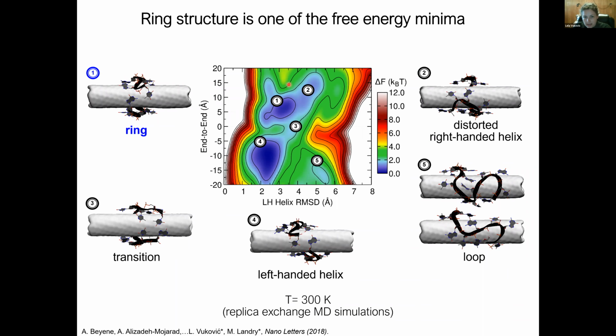And here is a free energy landscape. It's a 2-dimensional contour plot in terms of the relevant reaction coordinates in this system. What you should pay attention to is the color of the contour plots. The color represents the free energy of the system. The dark blue regions are free energy minima for these systems. Those are the conformations that the system likes to adopt. If you see red and other colors, those are higher energy conformations, which are less likely to occur in the system. And there are 2 free energy minima.